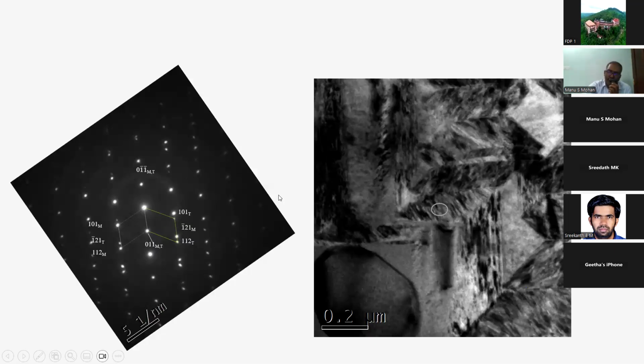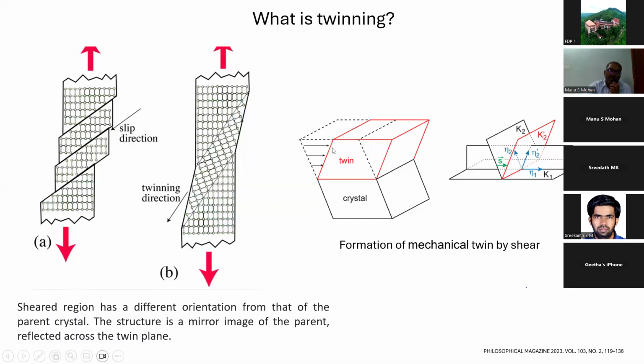So when I got this diffraction pattern, I simulated it. Before showing the diffraction pattern, you can see here twins - these are the crystals. When you deform it, you can deform either by slip or by twinning. Twinning is something you have already studied in your earlier education. In twinning, one part of the crystal is sheared relative to the other. So this is a twin in the crystal, and you are able to see it close to 5 nanometer scale.